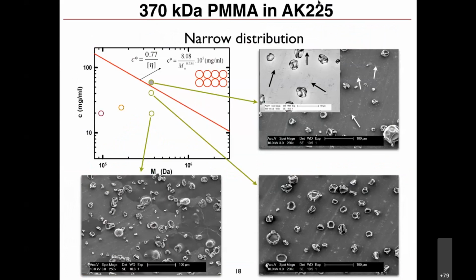It's in a solvent that evaporates very, very fast. It's called AK225. What I have plotted here is concentration in milligram per milliliter as a function of molecular weight, as the length of the molecule. And we know from literature and from what people have done that if you're above this line, it's called a C-star line. It means if you keep adding polymer to your solution, at some point you add so much that they start touching each other, right?